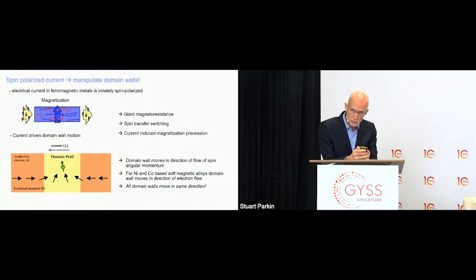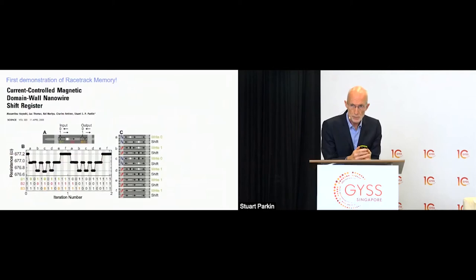And this is something that we first demonstrated in 2008 in a paper we published in Science, where we showed in a wire we could create a series of domain walls, we could pass current pulses, move all the domain walls in the same direction, and prove the fundamental concept of this racetrack. We could current control the presence of a series of domain walls in nanowires. And therefore, this proved this concept I proposed 6 years earlier was valid. And if you like, this is the first edition of this magnetic racetrack memory.